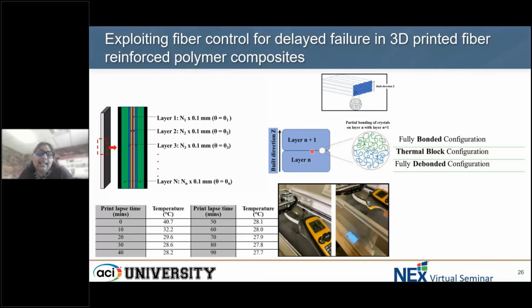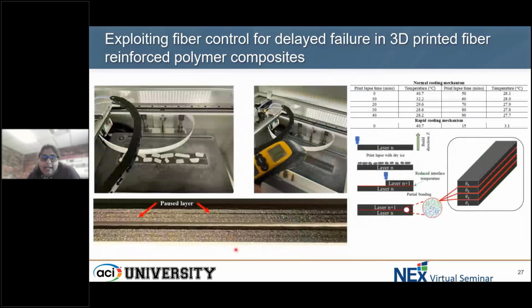So to print the next layer N plus 1, instead of having nice heated conditions on that interface, we now have a cold joint, which affects the polymerization at that layer. Of course, waiting 90 minutes for each layer is an impossible and unrealistic task. So what we did is we used what is called dry ice. Instead of taking 90 minutes to come down, that rapid cooling mechanism in just 15 minutes brought the temperatures very close to 0 degrees. So we were able to achieve faster and much lower temperatures in order to create that debonding interface between layers.